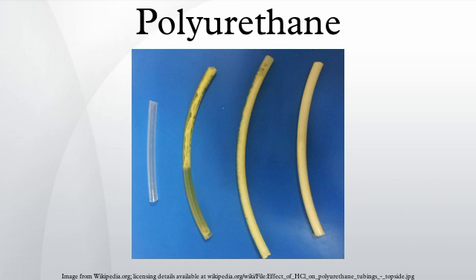Polyols for flexible applications use low-functionality initiators such as dipropylene glycol, glycerine or a sorbitol water solution. Polyols for rigid applications use high-functionality initiators such as sucrose, sorbitol, toluenediamine, and Mannich bases. Propylene oxide and/or ethylene oxide is added to the initiators until the desired molecular weight is achieved. The order of addition and the amounts of each oxide affect many polyol properties, such as compatibility, water solubility, and reactivity. Polyols made with only propylene oxide are terminated with secondary hydroxyl groups and are less reactive than polyols capped with ethylene oxide, which contain a higher percentage of primary hydroxyl groups.